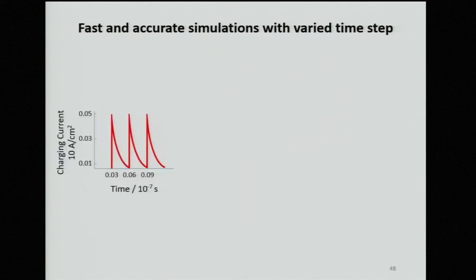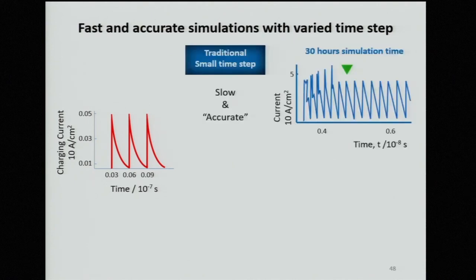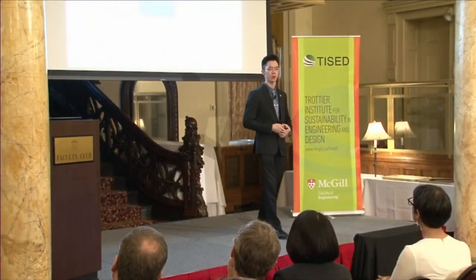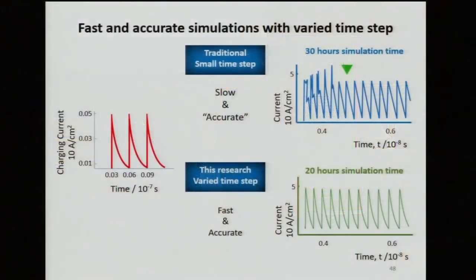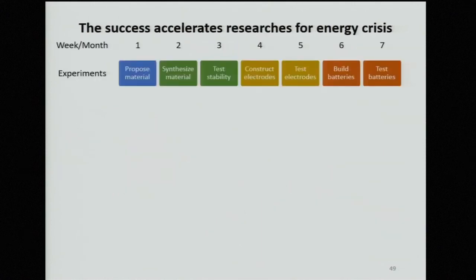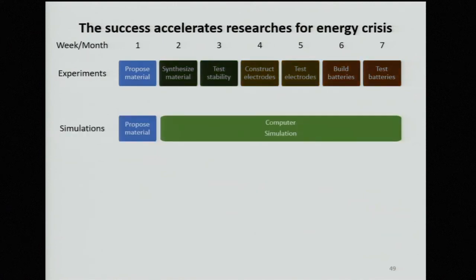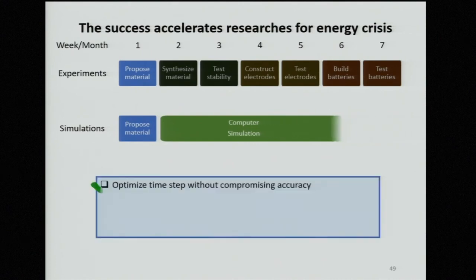So here we can see that if we want to simulate the energy storage of the supercapacitor, we have the method of using the traditional low constant time step, but this results in a slight error in the beginning, and a very slow simulation of 30 hours per run. By using our improved method of varying time step, we can reduce the simulation time to 1/3 of what we used to have, but still maintain the accuracy. The success of this research allows us to do rapid material testing instead of having a very intensive and long simulation time. The optimized time step will reduce it by 1/3, but still keep the accuracy.